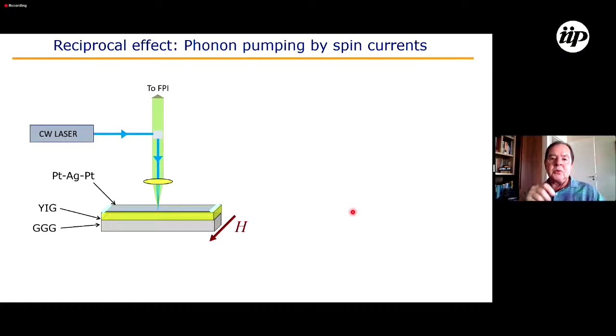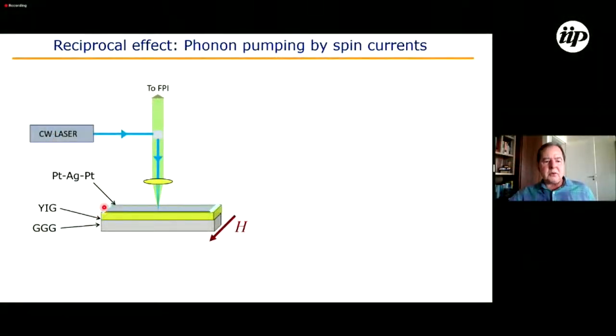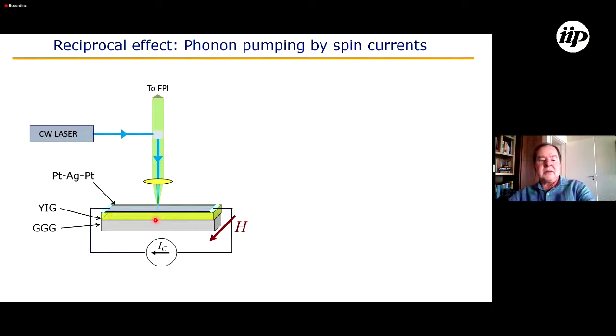Well, if phonons can produce spin pumping, in other words, produce a spin current, there should be a reciprocal effect. Spin currents can produce phonon pumping. And this was demonstrated last year with the following experiment. The experiment consists of having a film of platinum, which is a material with a large spin Hall coefficient. A current passes through this film. The current is converted into a spin current that goes into the YIG film. And what happens here is detected by light scattering.